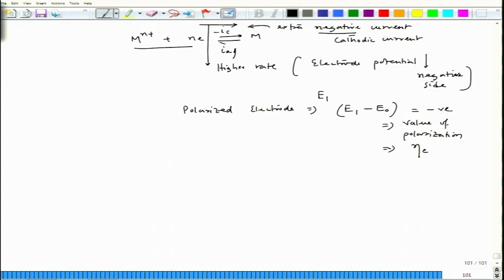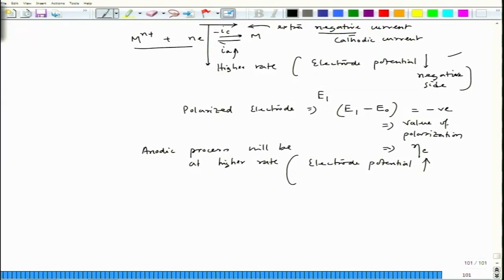Similarly, if we supply anodic current, then the anodic process will be at higher rate. The way we have discussed here, the electrode potential would increase from the standard value or the equilibrium value, and we also call it as polarized electrode. And that time, if the potential goes to E2, so E2 minus E0 is the positive quantity, since the potential has moved on the positive side, because we are actually taking this oxidation process at a much higher rate. So, this becomes the value of polarization.